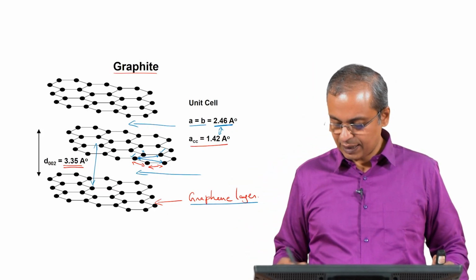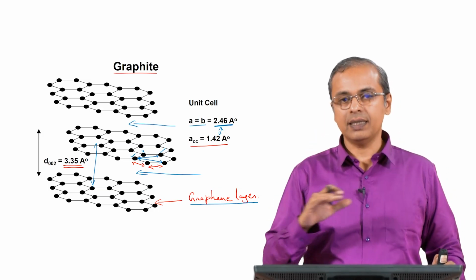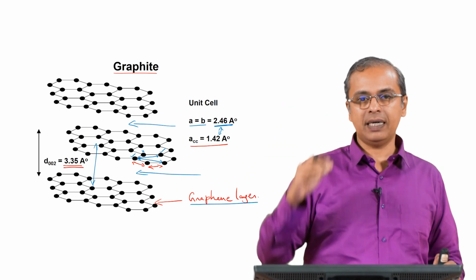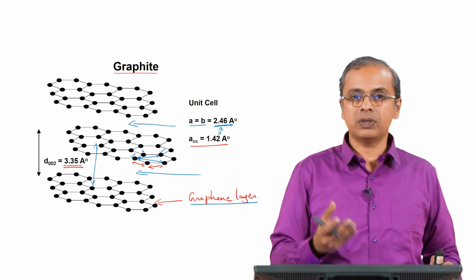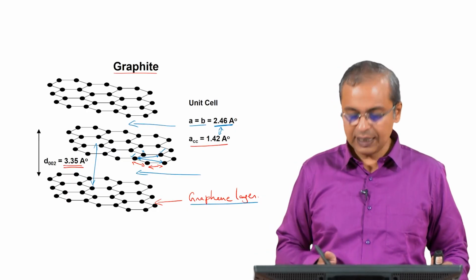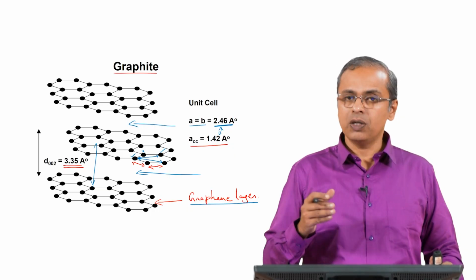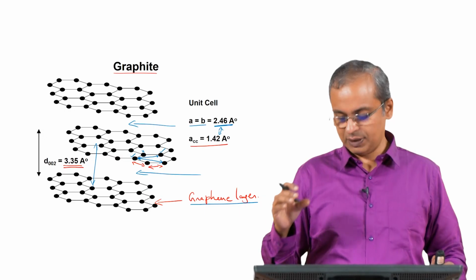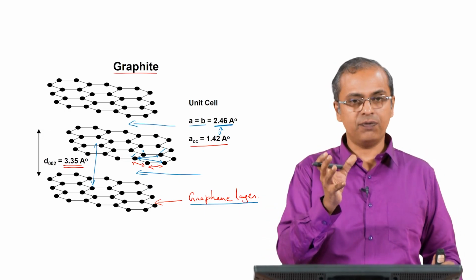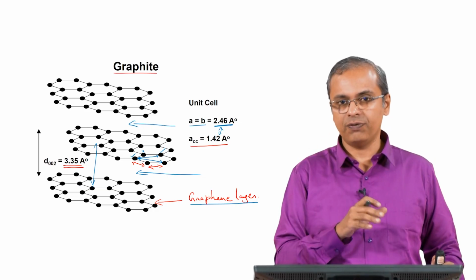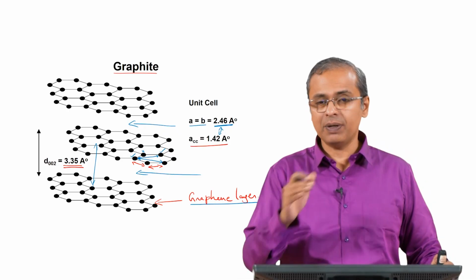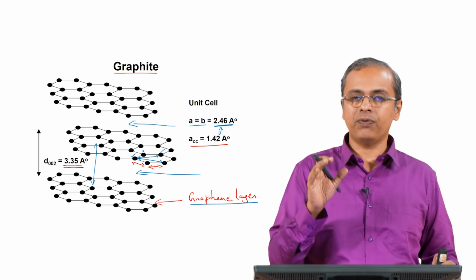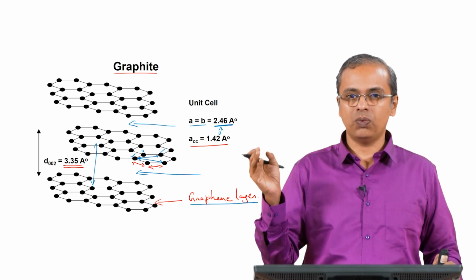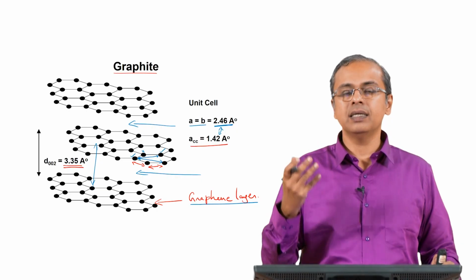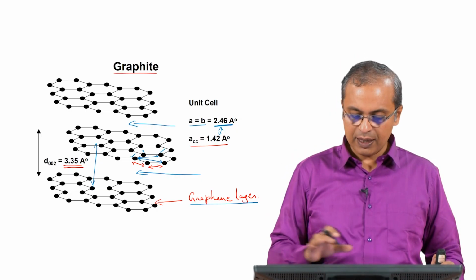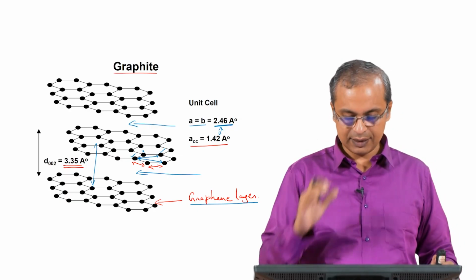This graphene layer, as I said, is originally how they used to define it. It is a single layer of this graphite structure. So, graphite has all these graphene layers stacked one on top of the other. Today when you hear a lot about research on graphene, although originally it was a single layer of these carbon atoms, today they look at a few layers of carbon atoms together, which is represented as graphene. They are looking more at the level of disorder in the structure, and as long as it stays above a certain level, they would still classify it as graphene based on the electronic structure as well. So there are some other parameters they look at before they call it graphene. It is not necessarily single layer graphene that you hear about in the literature. You can have multiple layers, and that is the context in which you have to understand it. So anyway, this is the way in which lithium can enter the structure, and that is lithium intercalated graphite.